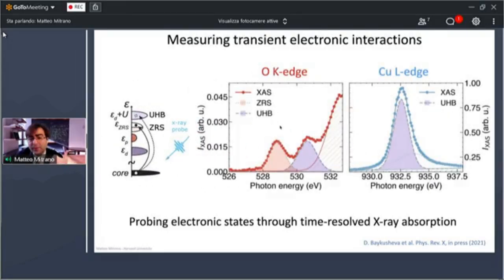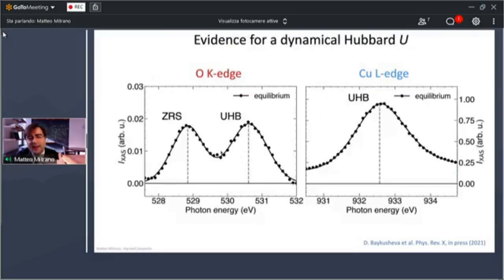And at equilibrium, what you see in this material at the two edges are peaks that are quite well defined. So you have at the oxygen K edge one transition for the Zhang-Rice singlet. You have one transition for the upper Hubbard band. The upper Hubbard band is really prominent at the copper edge. And what we find when we start doing our dynamic experiment is that we start with these peaks at equilibrium, the Zhang-Rice singlet and the upper Hubbard band at the oxygen K edge, the upper Hubbard band at the copper edge.